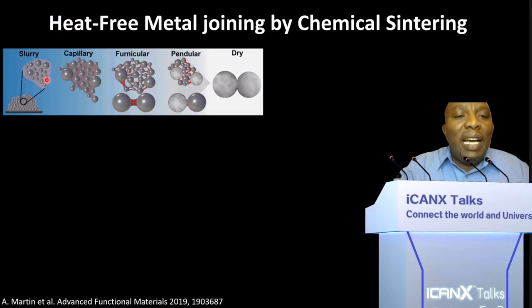When you have a slurry, as you dry it out, you can incorporate a dilute etchant. And as it evaporates and forms these capillary bridges, they become extremely concentrated in whatever etchant we have. And it will get to a point where it will locally etch a lot of the material on this oxide until the two particles coalesce. And if they do that, they'll form a neck where there is now an interconnect, and that interconnect will go all over the powder and form a well-connected metallic form.